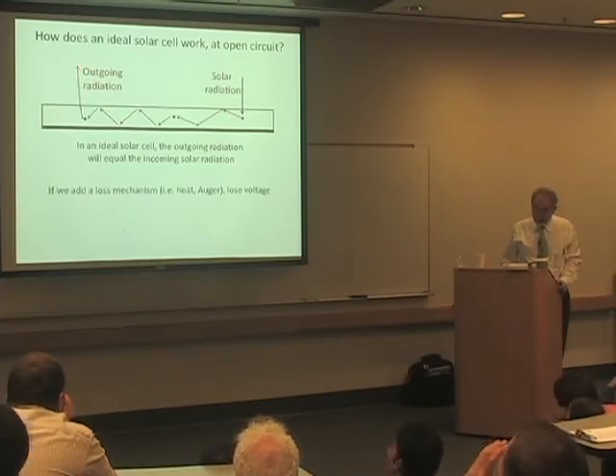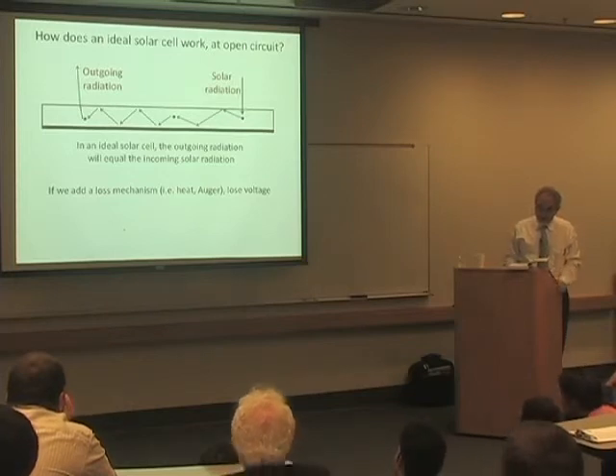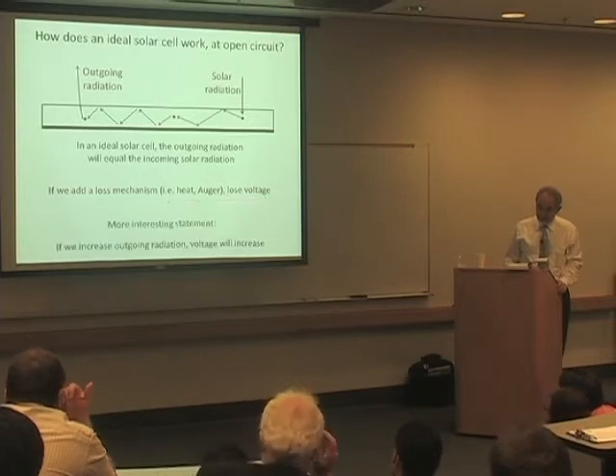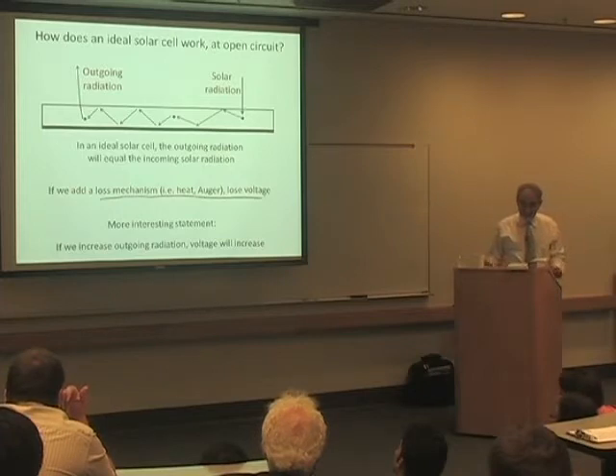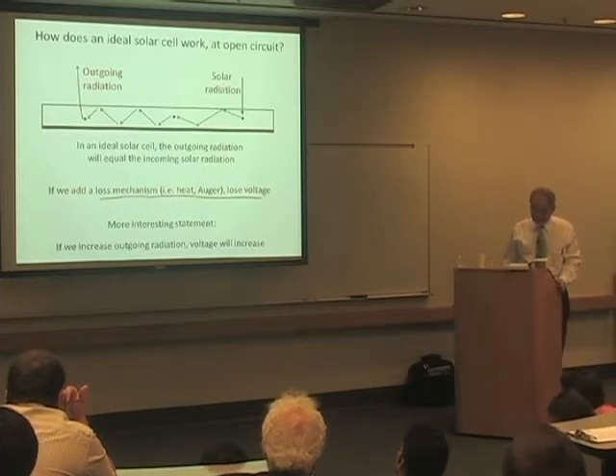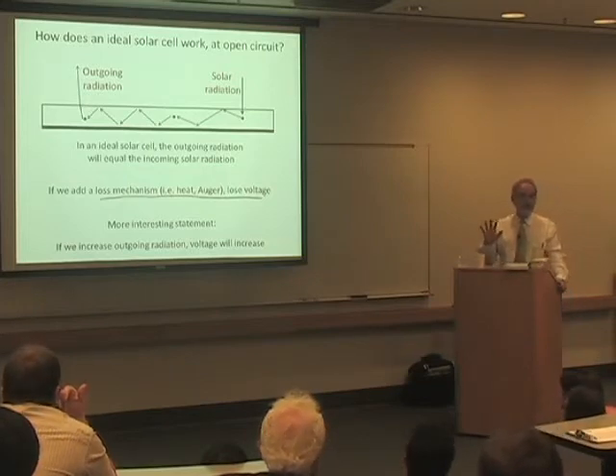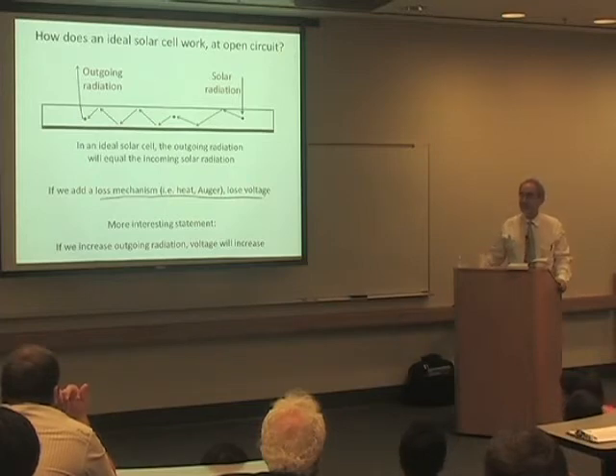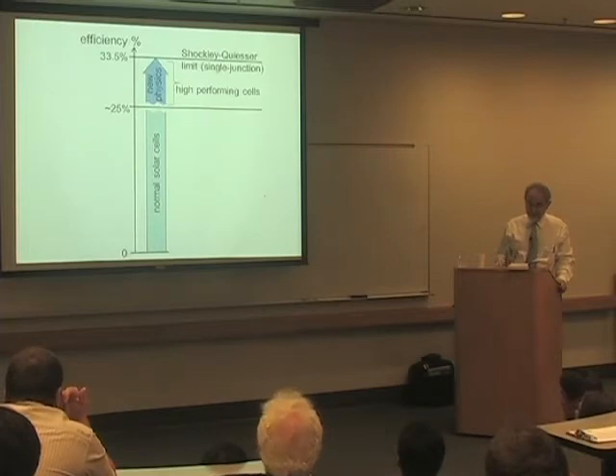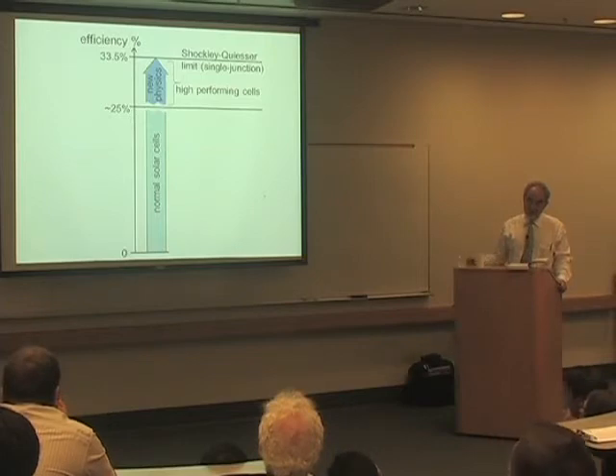Now, what this says then is that obviously if you add a loss mechanism, you lose voltage. But if you get rid of your loss mechanisms and get more of the external light coming back at you as luminescence, the voltage actually increases. So this leads to a very counterintuitive conclusion. It says if you want to make a really terrific solar cell, it should have the best possible external fluorescence, which is certainly counterintuitive.